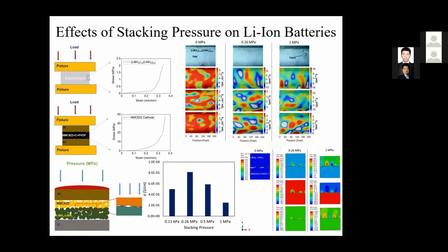Now, as before, if you now do the strain mapping, which we've done with digital image correlation, as you increase the pressures, you get initially uniform strain distributions across the different regions. But when you get to higher pressures, about 1 MPa, you start inducing cracking, which degrades the ionic conductivities of these systems. And so with methods like this, we're now developing lithium-ion batteries with pressure-assisted fabrication processes in ways that are translating to interesting systems for further studies.